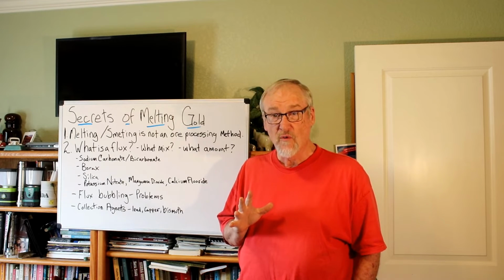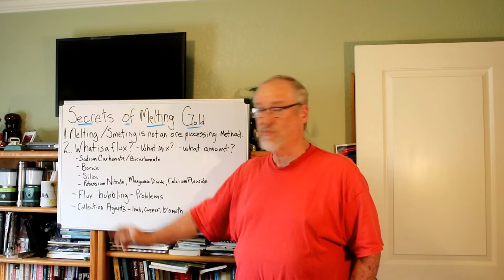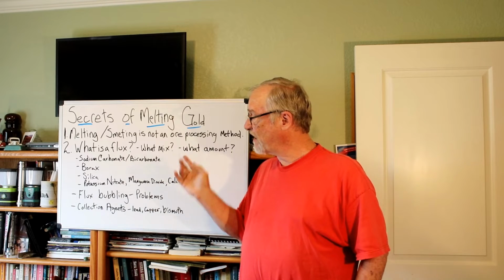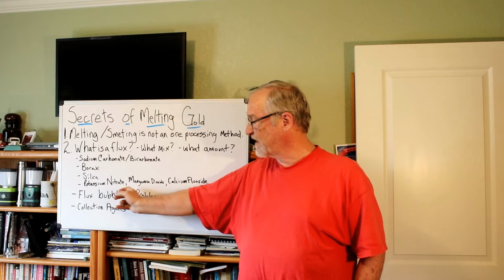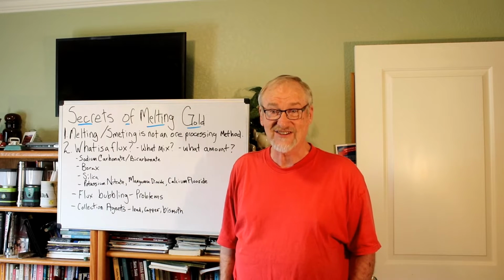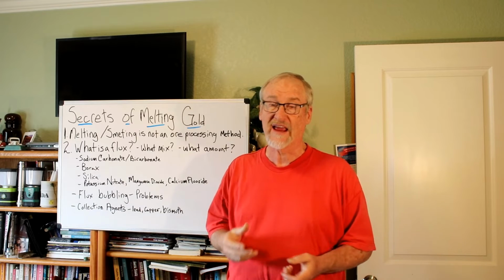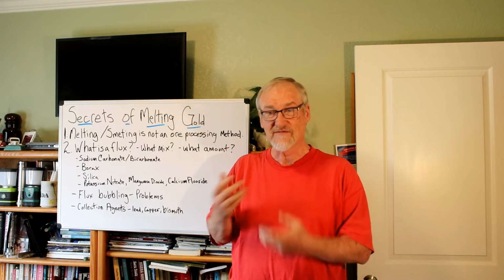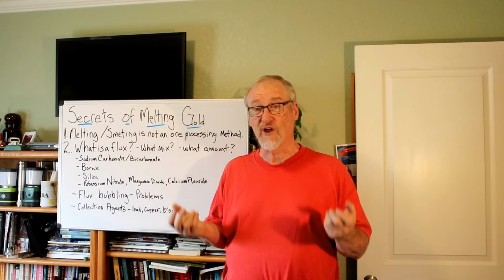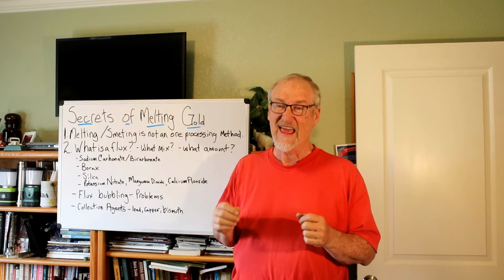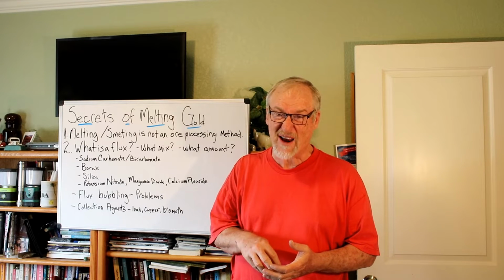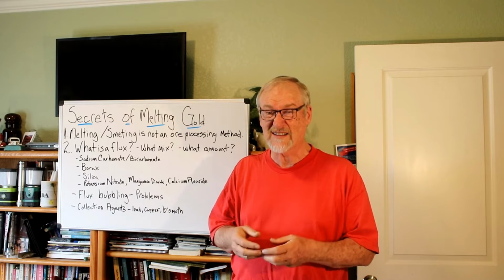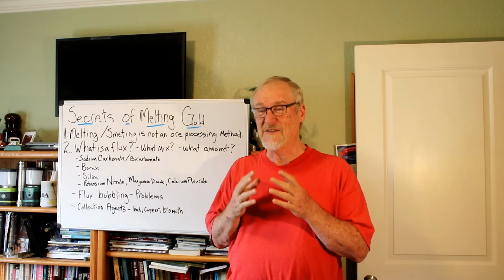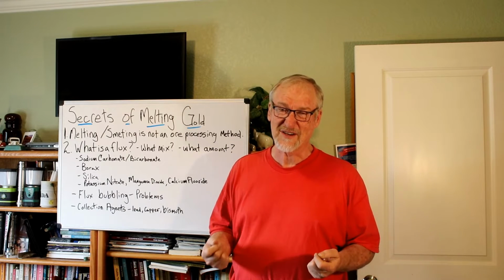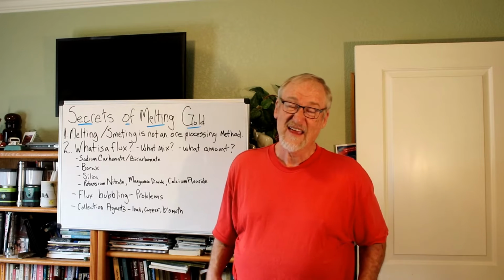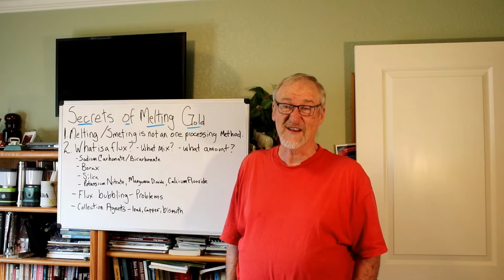There are problems with fluxes, and bubbling is one of the biggest ones. If you put in bicarbonate or any of these oxidizers, both potassium nitrate and manganese dioxide and yield oxygen, and it just causes bubbling. And if you haven't melted your gold yet and your flux starts to bubble, it may overflow the crucible that you have, which is a really bad thing. If the gold hasn't melted yet, it may not be on the bottom. It may be still mixed with the liquid flux, and you may spill and lose gold. Even if you don't lose any gold, it's still the spillage of molten flux. It's like lava. It will wreck whatever your furnace is, or however you're doing it.